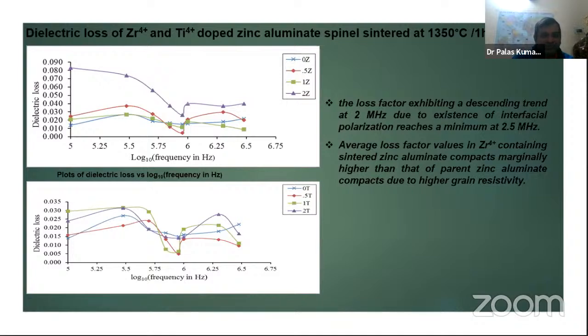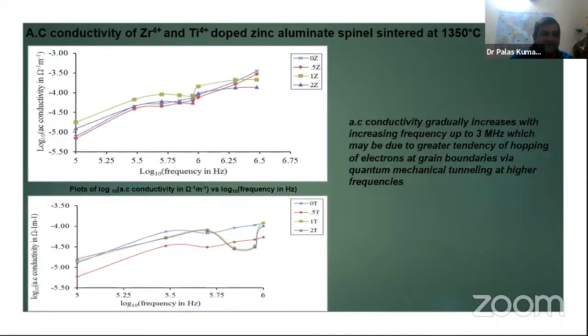So it is a unique combination, and two things are very important: not only the capacitance or dielectric constant, but the loss is also important. The inverse of the loss is basically the quality factor, right? So these properties are very important to design microwave elements and compounds. And if we see the AC conductivity, which we can derive using the basic formula, we know that AC conductivity is 2 pi f tan delta times the permittivity.